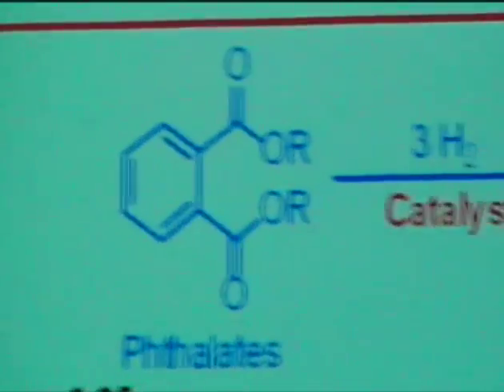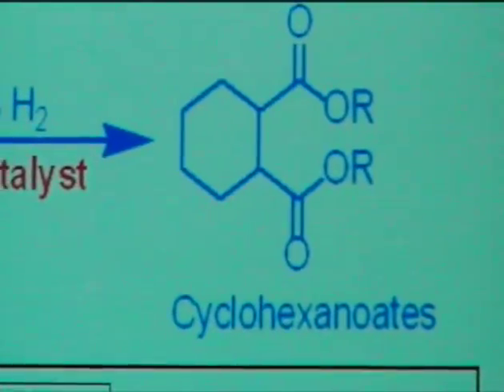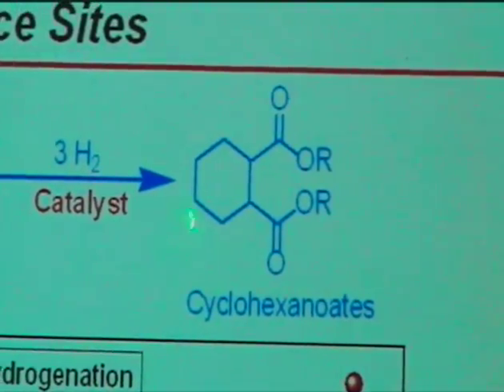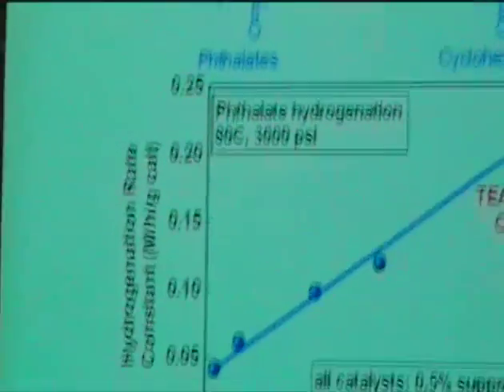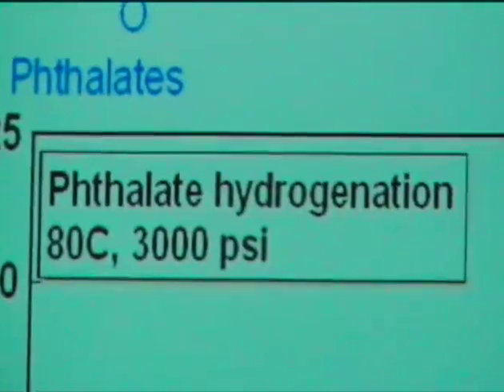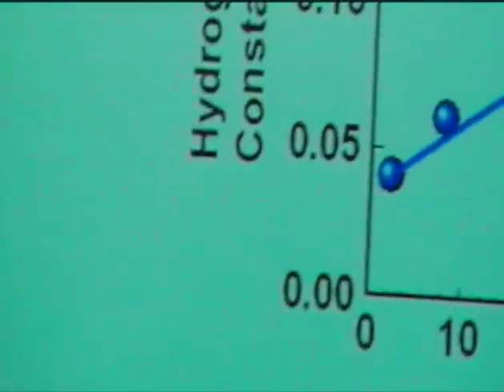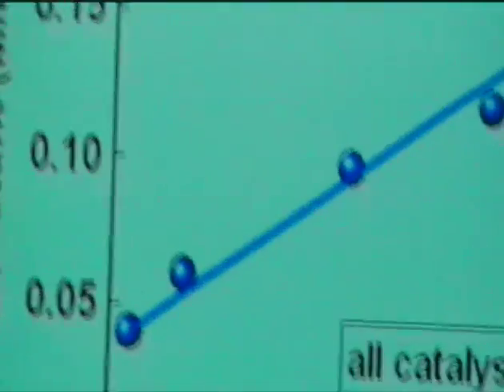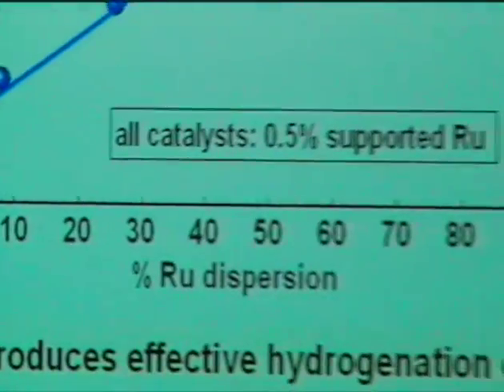And we went ahead and looked at some of these. So here's a variety of different ruthenium on silica catalysts. This was the reaction we were interested in. It's this hydrogenation of the phthalate, hydrogenating the aromatic ring without bothering the ester functionality. And you can see all of these are 0.5% ruthenium on silica.